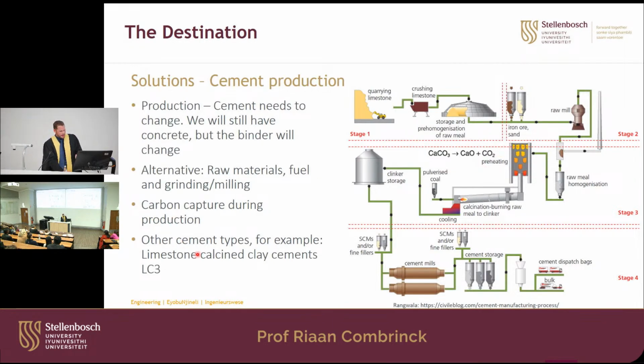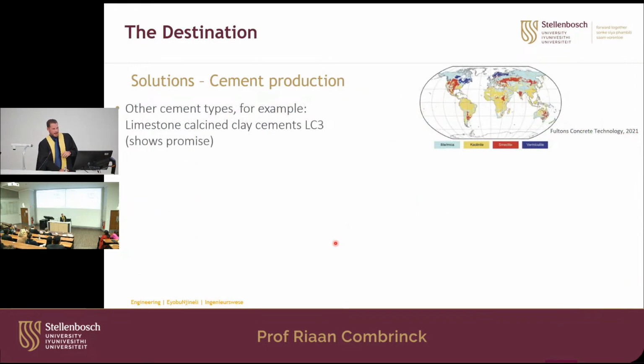Then there's also other types of cement that we can use. There's this LC3 cement, which is a limestone calcined clay cement. The reason why it has so much potential is because if you look at the clay deposits all around the world, there's a lot of clay. It's similar to limestone. That's why concrete is so successful, because there's a lot of lime all over the world and you can make it all over the world. And the problem with things like slag and fly ash is their limited availability, but clay is available worldwide.